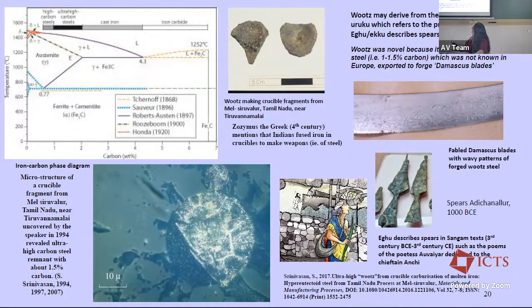And the interesting aspect about wootz steel is that, as I said, it was an ingot of about 1.5% carbon, and that is typically made by carburizing wrought iron along with carbonaceous materials so that the carbon got into the steel and improved its qualities. And then I spoke about this typical banding of pearlite and cementite, which was also sought after, apart from the properties of the steel itself.